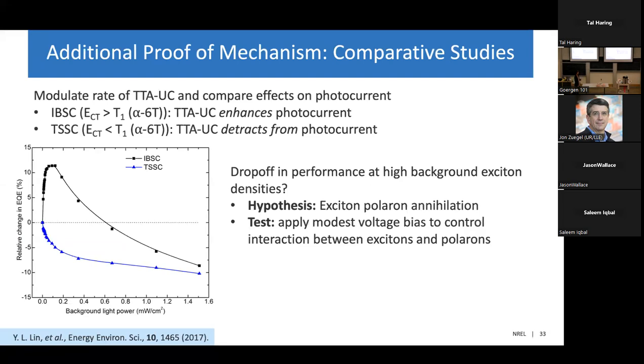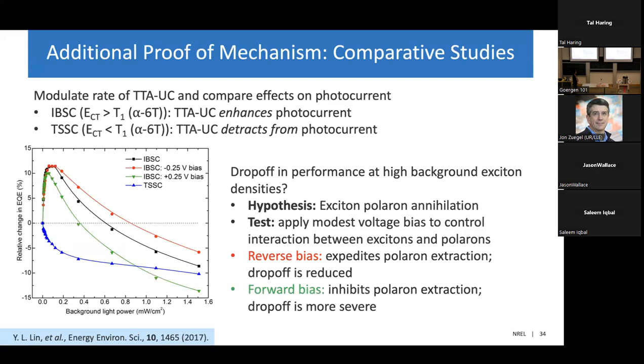So to test this, we applied a modest voltage bias to the solar cell at the same time. And we applied a reverse bias that basically sucks the polarons out of the device more quickly, so they have less time to interact with the excitons being probed. And you can see that the drop-off is now reduced in this red curve. On the other hand, when we apply a forward bias, that's going to inhibit polaron extraction, and you can see the drop-off is more severe.